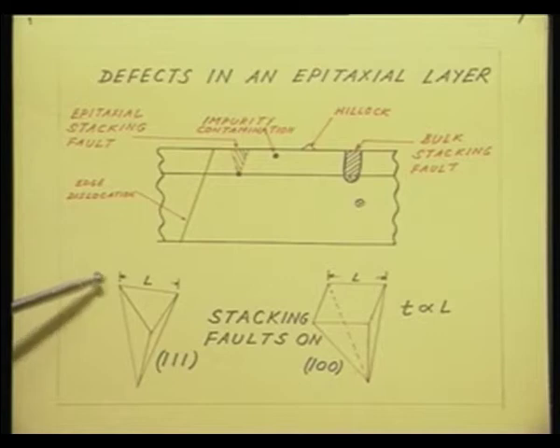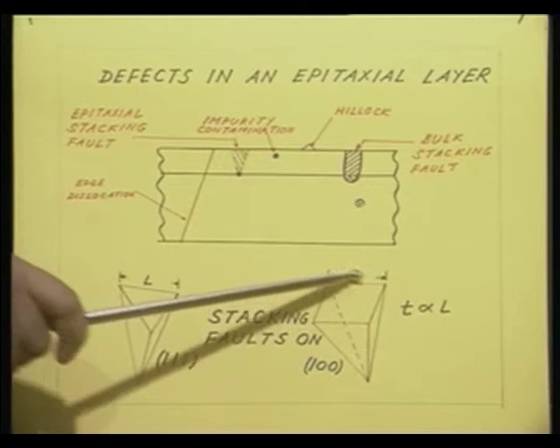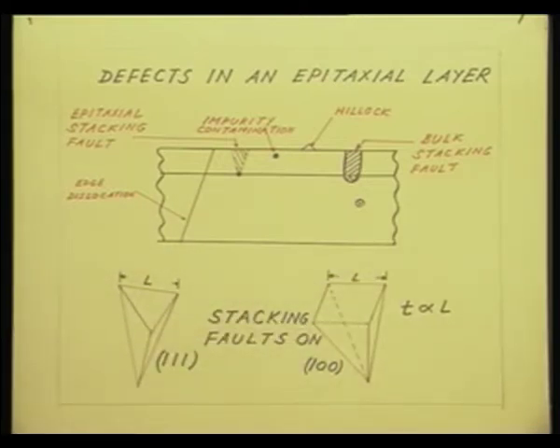So, under the microscope you can measure the length of the side of the pit, and that is going to be proportional to the thickness. The proportionality constant of course is going to be different for the different crystal surfaces, but it is going to be proportional. So, once you know the substrate crystal orientation, you can easily calculate the epitaxial layer thickness simply by looking at these stacking faults under the microscope and measuring the side. In both cases this is true. Here the side of the triangle I am calling L, here I am calling the side of the square or the rectangle L. This will give you a good idea of the epitaxial layer thickness without having to resort to other techniques, a simple, ready to use way.